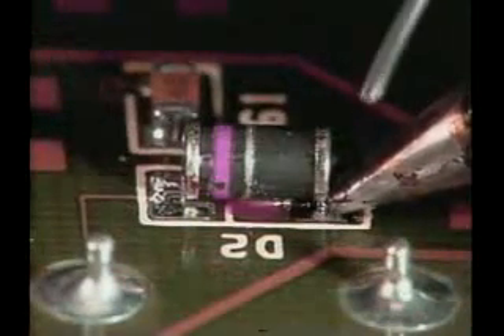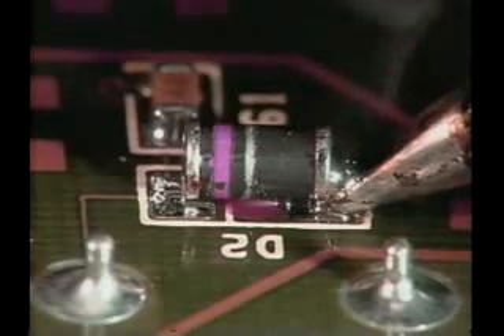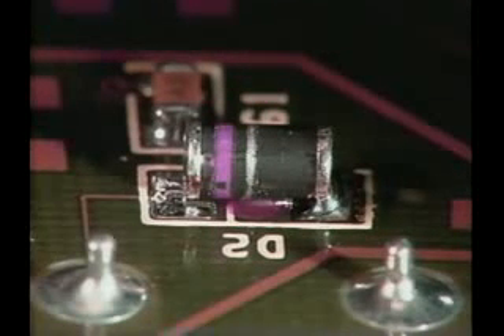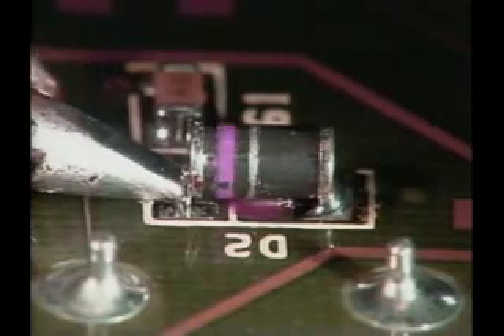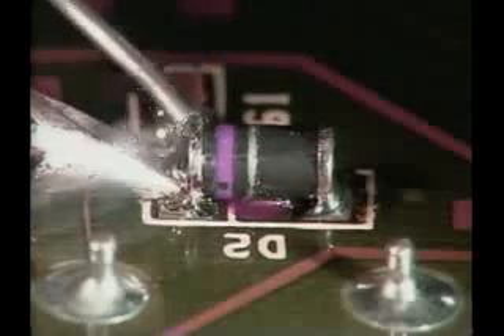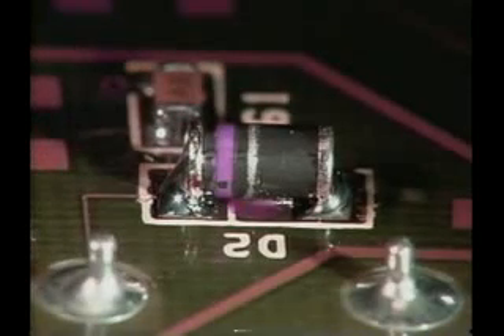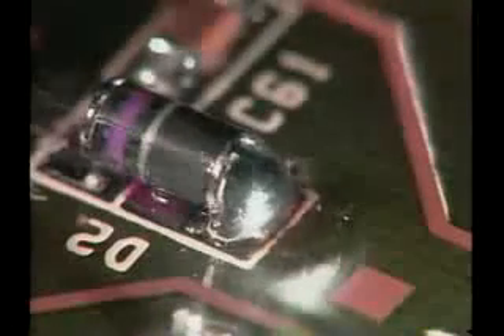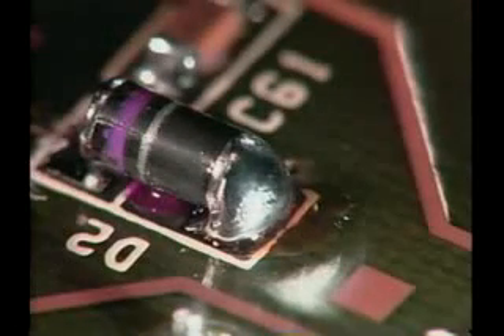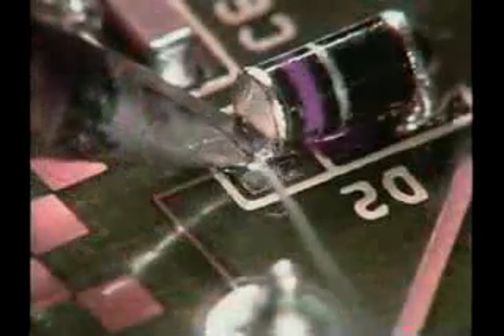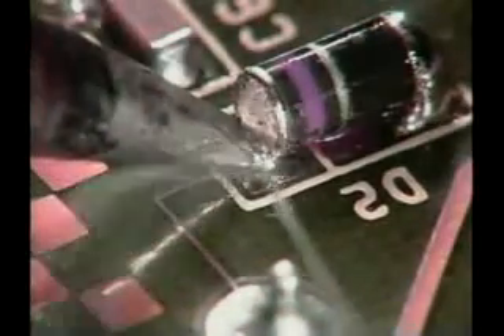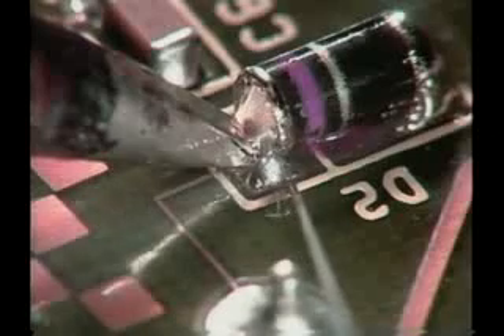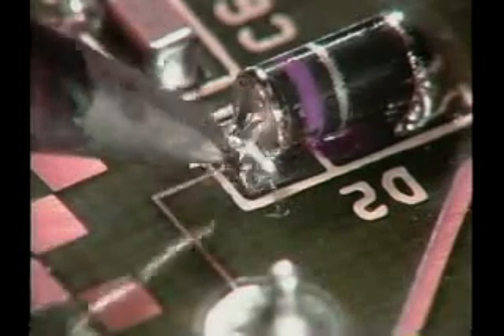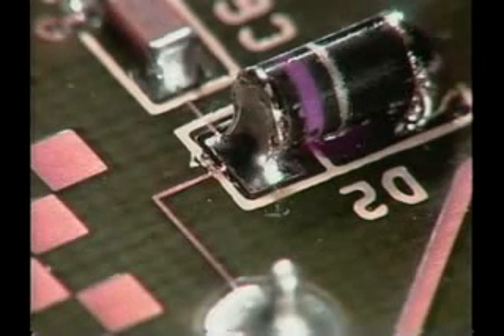We'll be using flux cord solder and the largest tip you can safely use without damaging the board or any adjacent solder joints. The size of the solder wire is also important when soldering small components. If the solder is too thick, it's easy to melt too much solder into the joint. If the solder is too thin, it can take too long to melt the right amount into the joint. In this case, you would have to leave the heat applied longer, which can cause thermal damage to the board.